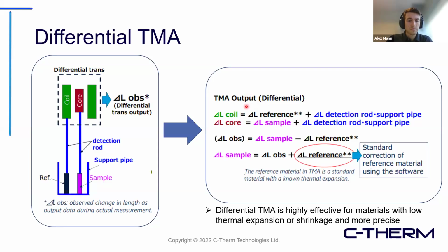So as we can see here, the coil and the core both have the detection rod and support tube. The observed is the sample minus the reference because these two cancel out. We know the observed, this is measured. We know the reference because the reference we use is a standard with known values. So just by doing simple rearranging, we can easily determine to a high degree of precision the expansion of the sample. And that's kind of the beauty of it.